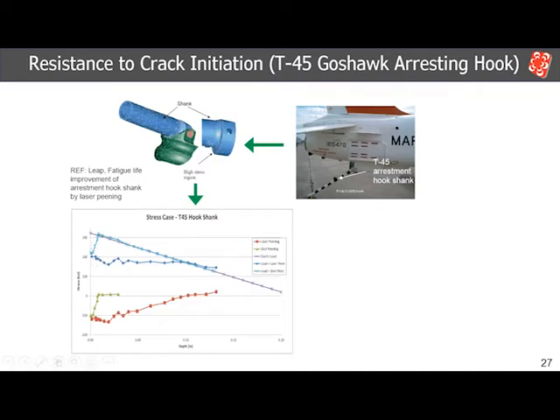In shot peening, you are able to drop the magnitude at the surface, but because of the shallower depth, the material is still experiencing a stress level above 300 KSI just below the surface. Whereas in the case of laser peening, the material is only subjected to a stress that is 200 KSI or even lower. So the material, especially in that critical location where the failures are happening, is now experiencing a much lower stress magnitude than with shot peening.